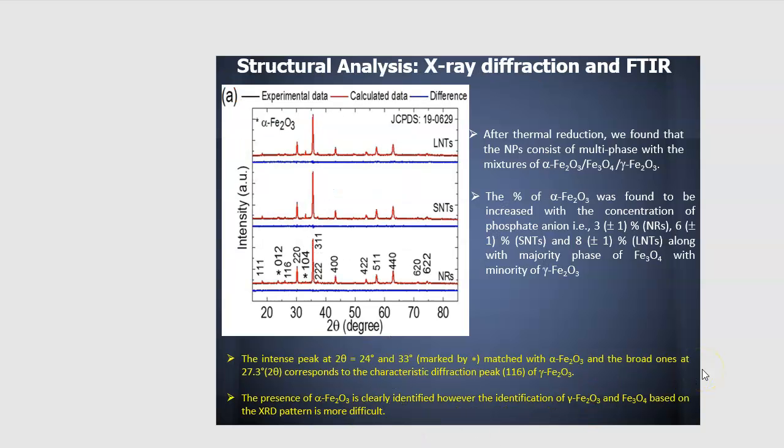And this is the XRD data. Here you can see after thermal reduction, we found that the nanoparticles consist of multiphase, a mixture of hematite, magnetite and maghemite.